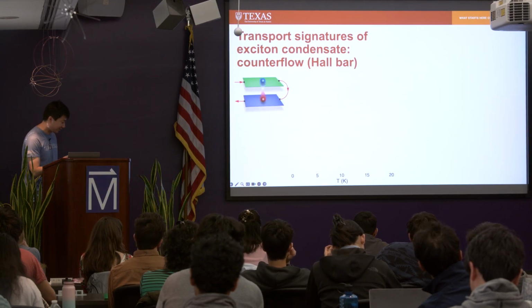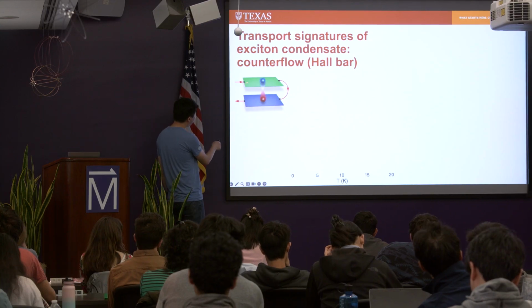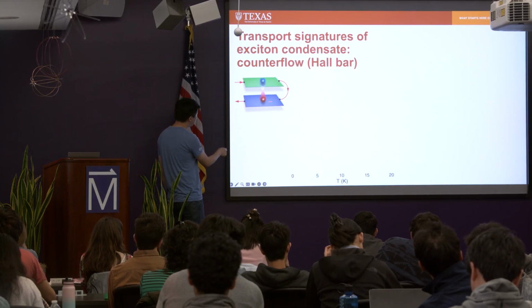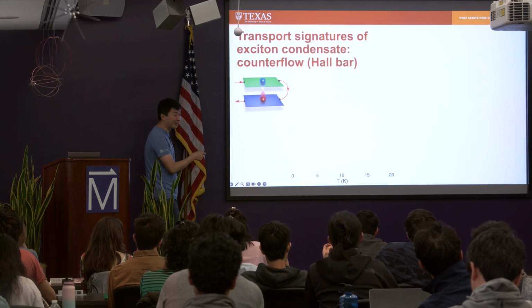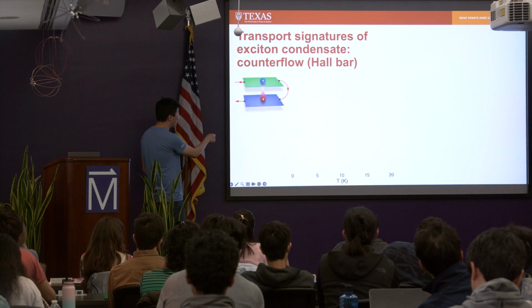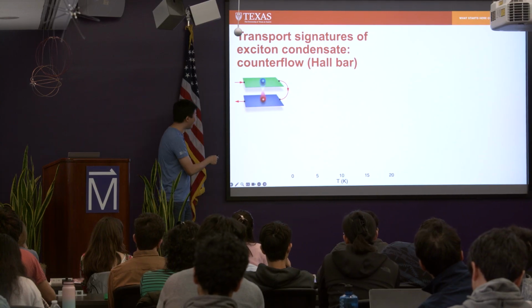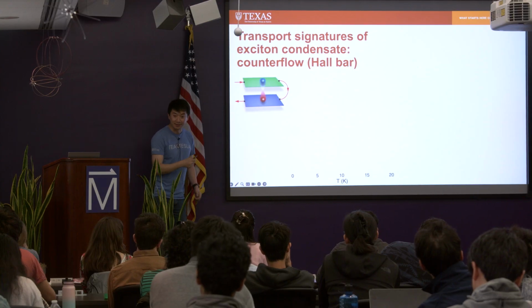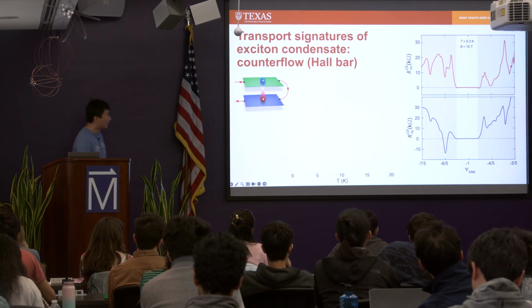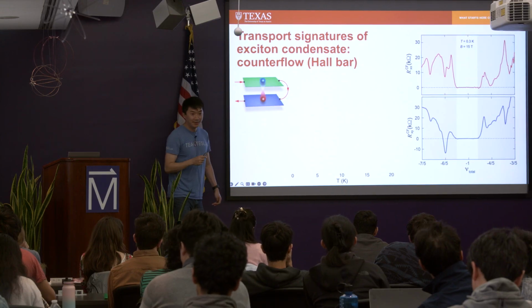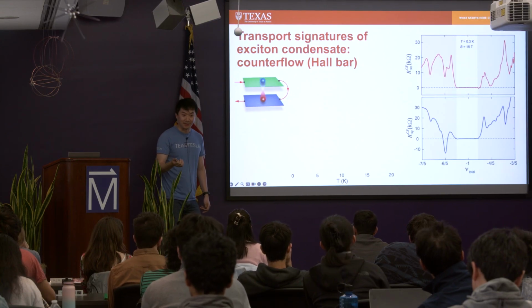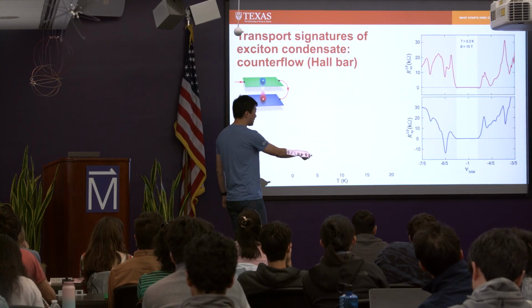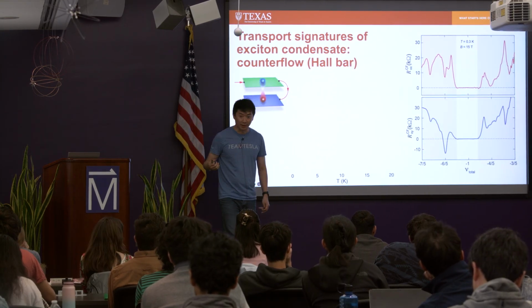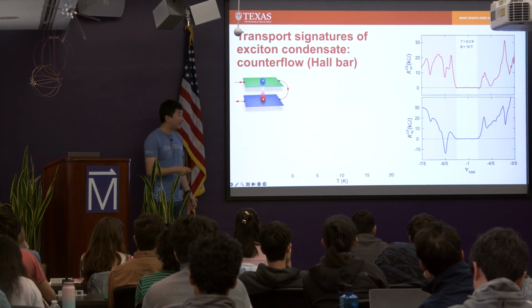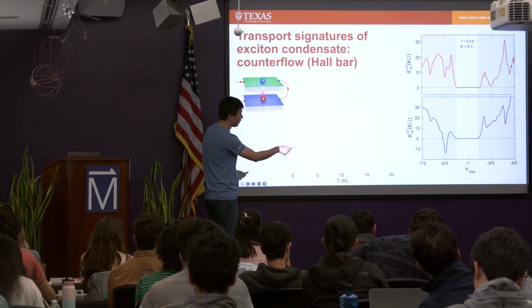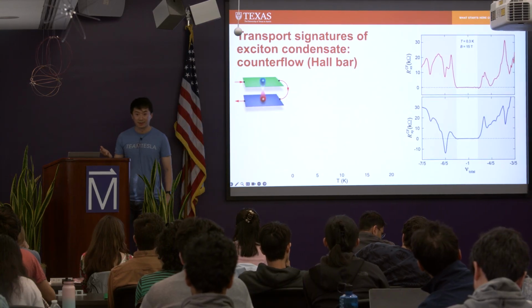Or you can also do this in a slightly more straightforward way. You flow current from left to right on the top layer, and you just feed it back and flow the current in the opposite direction, right? The advantage here is that because the exciton has opposite charge, electron and hole, when you flow current in the opposite direction, you're actually moving the exciton on its own, right? And when you look at the transport response, the exciton is overall charge neutral, so it does not experience any Lorentz force, right? And when you flow exciton in the bulk, the transverse resistance in this configuration is 0, meaning that what carries current is something that's overall charge neutral, right? And at the same time, longitudinal resistance is also 0, meaning that when exciton flows, it flows dissipationlessly, right?